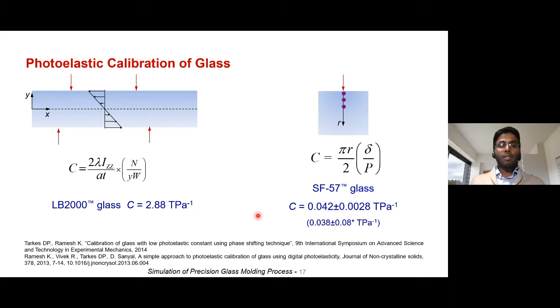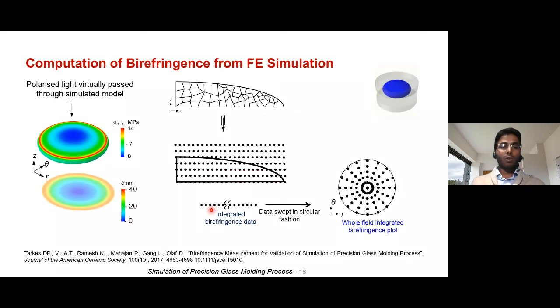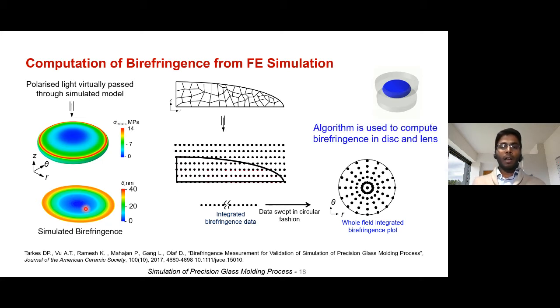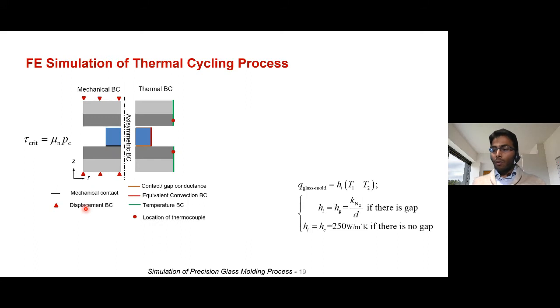So once we have this photoelastic calibration constant from the experiments, you can substitute back in this equation over here, and then you will be able to compute the birefringence data. So this data is the simulated birefringence data and not the experimental one, but this can be compared directly with the experiments.